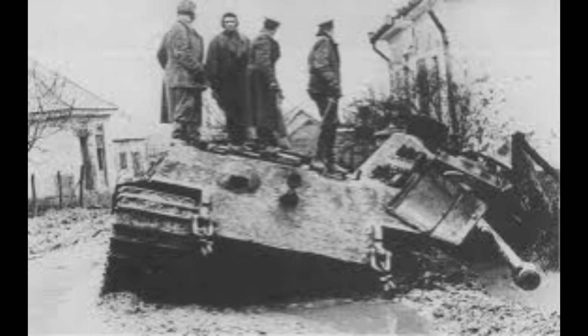A turret manufactured in November 1944 showed noticeably degraded quality. Irregular bead profiles, variable penetration, increased defects, questionable heat treatment. Metallurgic examination revealed welds approximately 80% of base metal strength.